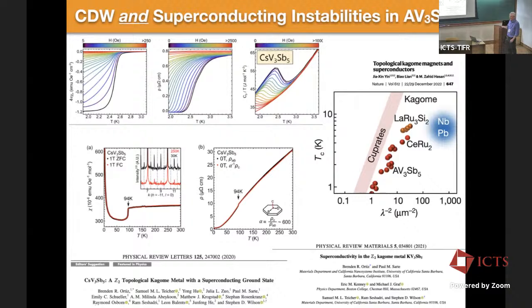And one of the very exciting things, which was discussed, well, at least published a year later, was that in cesium vanadium antimonide, and actually in the other two members as well, they have superconducting ground states, which were initially identified. This is the heat capacity data here with a TC that's around 2.5 Kelvin. And actually, when I saw this data initially, I thought that this was the first superconducting ground state in a Kagome material. And actually, the literature is a little vague on how many other Kagome materials there are, metallic Kagome materials that have superconducting ground state.